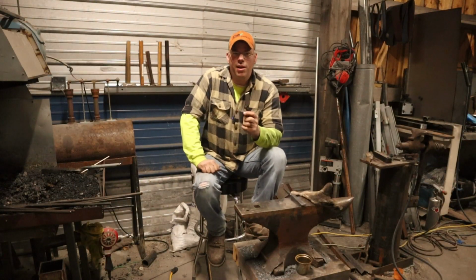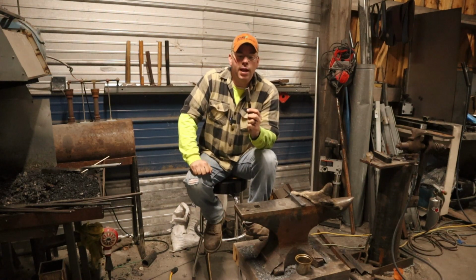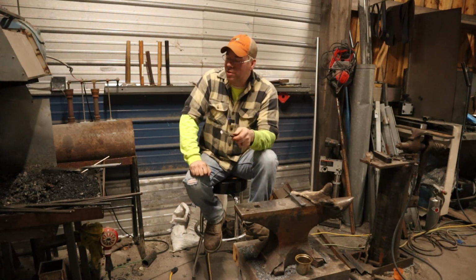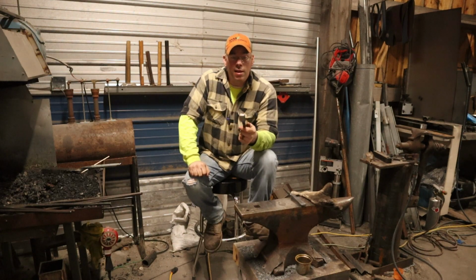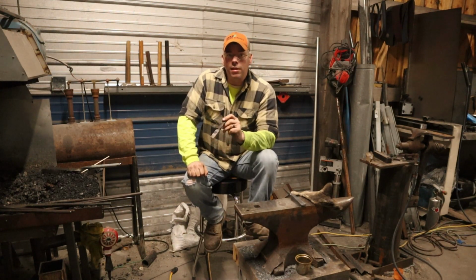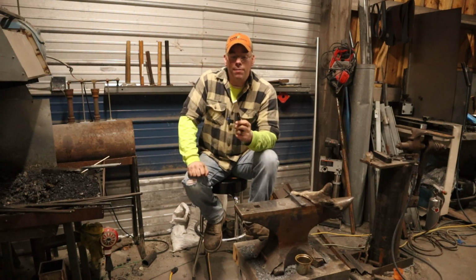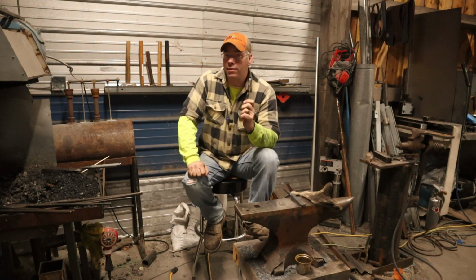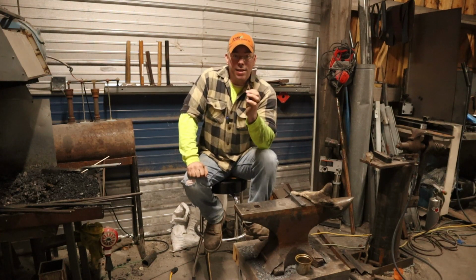I forgot to preheat my quench oil a little bit. What I do before I go to quench something, especially as cold as it is outside, is usually heat a piece of mild steel up, stick it in there and get the temperature of that oil up some so it doesn't cool the metal down too fast. And that's what happened with this. It cooled it down too fast and I developed a whole bunch of cracks in it.